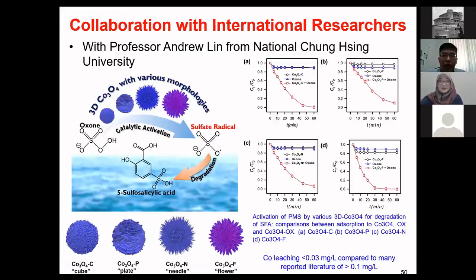Okay. And I just want to highlight some of the recent innovations with my international researchers. This is from Professor Lin from Taiwan. What we look into is controlling the cobalt oxide morphology. We control it from cube structure to flower structure, right? And our interest is to look into how we can use different morphology to reduce the catalyst leaching. In fact, catalyst leaching can be controlled very well if you use a suitable morphology. For this case, the leaching is a lot lower than the normally reported leaching. For example, a lot of people report more than 0.1 milligram per liter, but for our case, less than 0.03 milligram per liter of catalyst leaching.